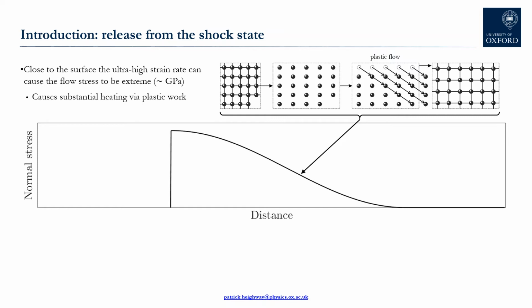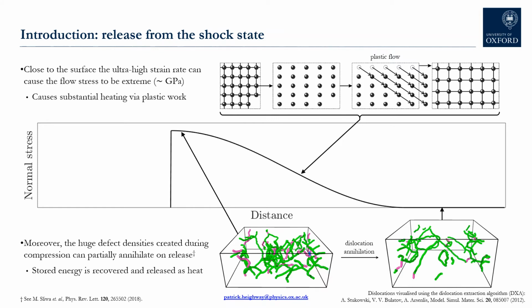We now also have strong experimental evidence of reversed plasticity during shock release, which can cause some fraction of the huge defect density nucleated on shock to be annihilated, so the energy stored by those dislocations can be partially recovered during shock release and released as heat. So the purpose of the work described in this presentation is to explore the role of plastic work and this defect energy recovery, and to see whether these heating mechanisms can beat thermoelastic cooling.